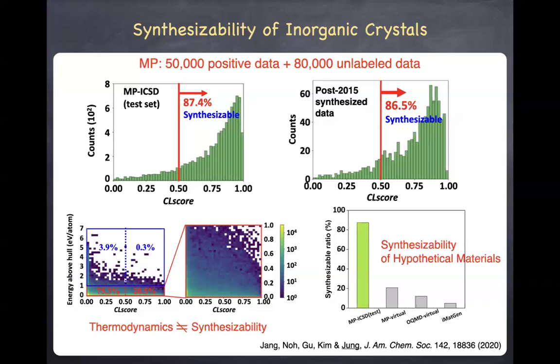And in short, we call it PU learning. And so we've done that. And we've used Materials Project database, which consists of about 50,000 positive data and about 80,000 unlabeled data that are really obtained by the elemental substitution of the existing synthesized compounds. So we've done this PU learning for this inorganic compound database, and our model has about 87% recall accuracy, meaning that 87% of the time we will predict the synthesized compound as synthesizable.